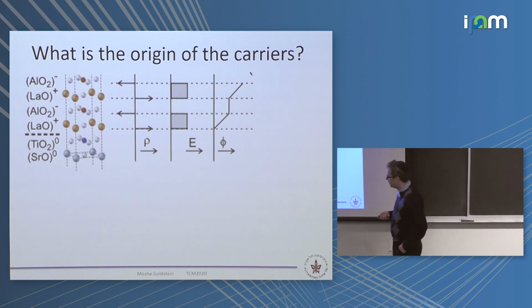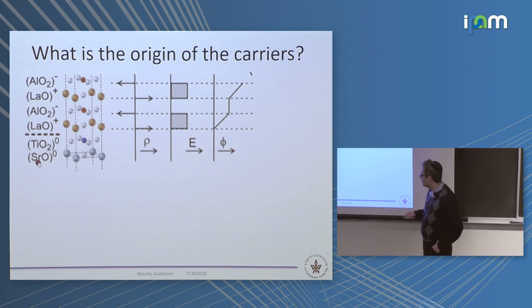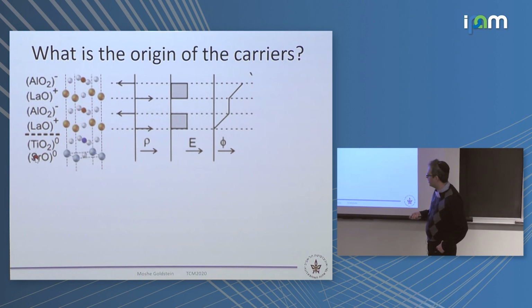And the idea is as follows: if you look at the charges of the strontium, titanium, etc. in the presence of oxygen, it turns out that in strontium titanate, the different layers are electrically neutral, whereas in lanthanum aluminate, the different layers are actually charged by plus and minus. So if you have those layers, plus, minus, plus, minus, it's like a series of capacitors. You have an electric field which is finite and nonzero, and then the potential accumulates from layer to layer. It's like capacitors in series. And this can definitely not go on, because eventually you'll create a big potential difference between the 2 sides, which will become bigger than the band gap.